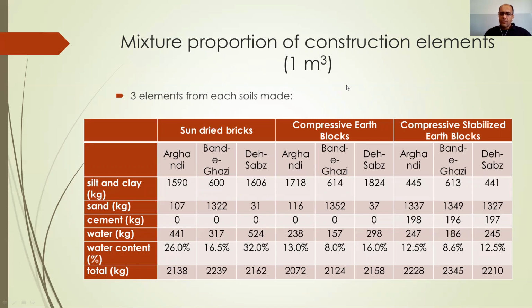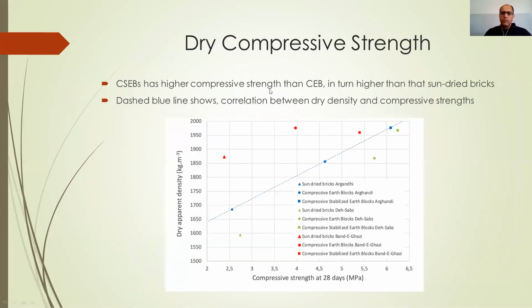For the mixture proportion, from those three soils, we developed three types of elements, like sun-dried bricks, which we use traditionally, and two modern elements like compressed earth blocks and compressed stabilized earth blocks, which we add cement to. The dry compressive strength of these three elements shows that CSEB, which has cement, has higher compressive strength than CEB without cement, and in turn CEB has higher compressive strength than sun-dried bricks. This dashed blue line shows correlation between dry density and compressive strength. It shows the more the dry density is, the more compressive strength we get out of these elements.